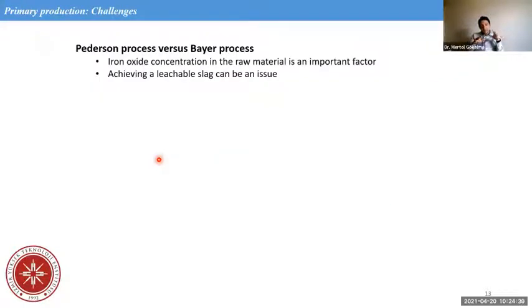To summarize the primary production part, the Pederson process versus the Bayer process. Iron oxide concentration in the raw material is a very important factor as a challenge, because it will change the feasibility. So if the ore does not have a very high iron oxide concentration, then that first reduction, the pyrometallurgical reduction, can be unfeasible. And this is the biggest challenge. And the second biggest challenge is achieving a leachable slag to produce the alumina we target.